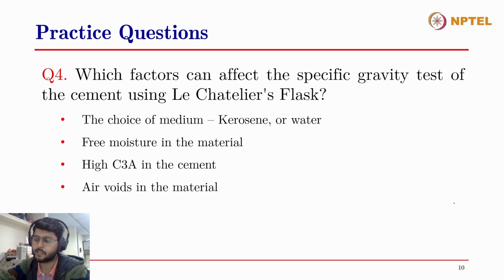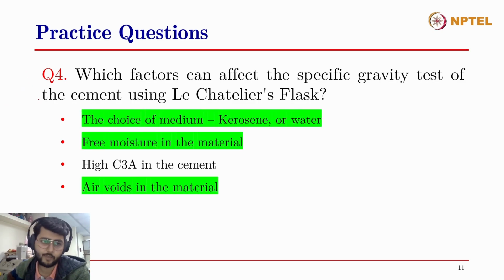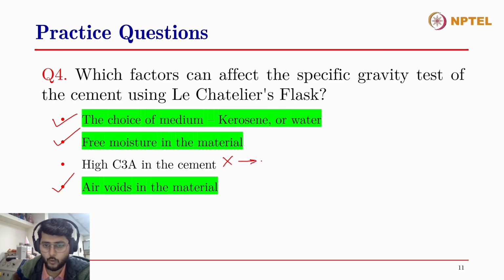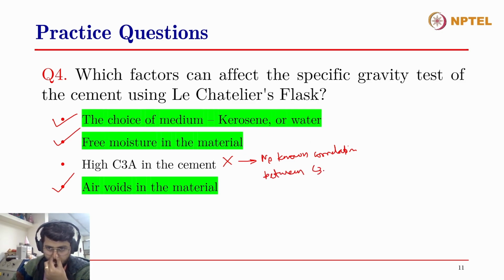Alright, the correct answers to this question are the choice of medium, kerosene or water, free moisture in the material, and air voids in the material. It could not be related to the C3A. I mean, there is no known correlation between C3A content and specific gravity of cement.